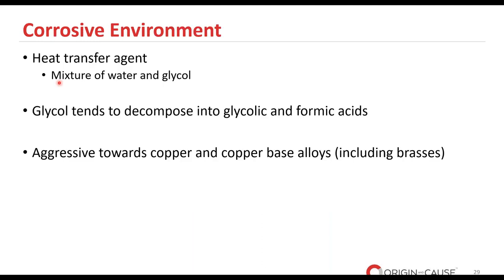One of the critical factors we considered in our analysis is the surrounding environment. And the component in question here was in constant contact with a heat transfer agent. Specifically, it's a mixture of water and glycol. A concerning issue in this case is the decomposition of glycol. It can break down into glycolic and formic acids over time. And both of these acids are notably aggressive towards metals, particularly copper and its alloys, including brass. The corrosive environment likely promoted wear and deterioration, potentially leading to the failure that we observed. The vulnerability of such materials in this environment always demands careful consideration and monitoring.